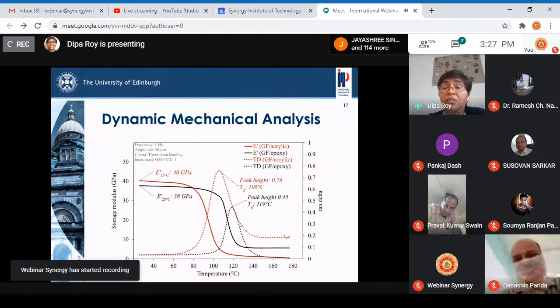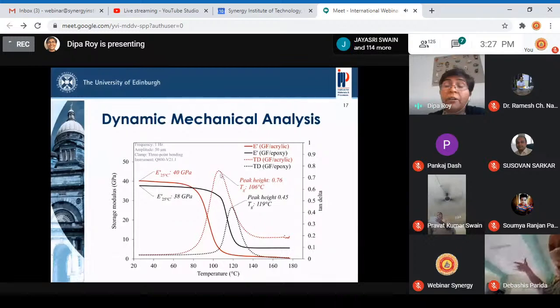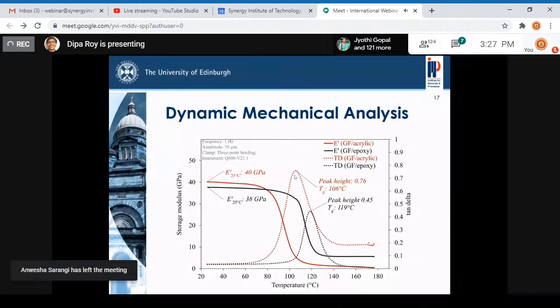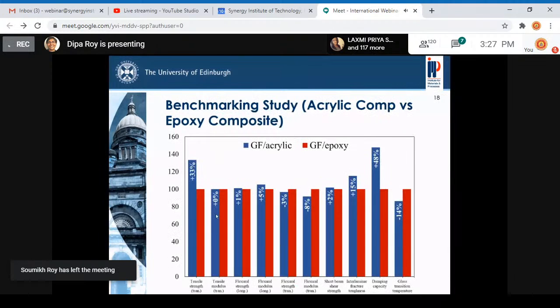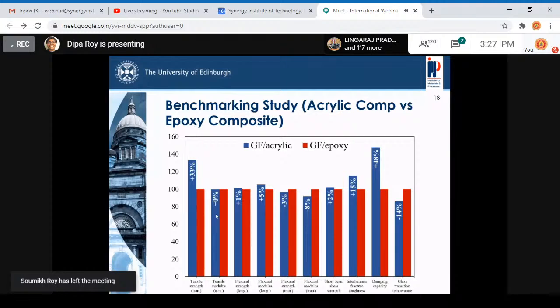What we expected is a high damping property for this acrylic composite. Here we can see the damping parameter tan delta is much higher. This is what we expect from a thermoplastic composite anyway, so it was no surprise. But the storage modulus values were pretty close. So overall, the indication of the mechanical property, or the elastic component, of the composites was quite close, which is a good positive sign. I will not go into detail of the mechanical characterization, but this is just an overall view of what we observed by a thorough mechanical characterization.